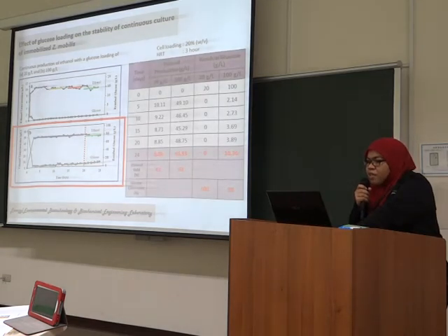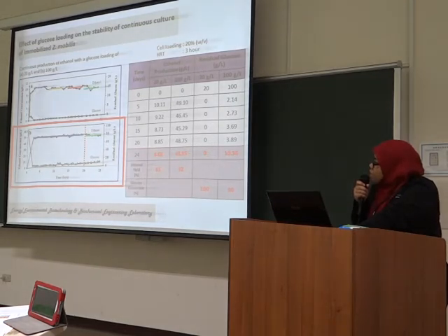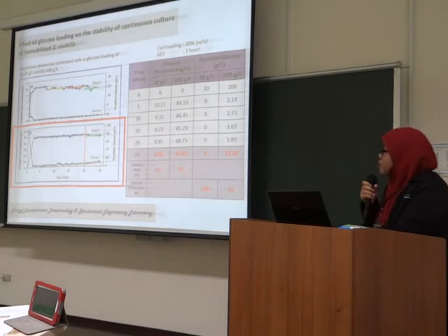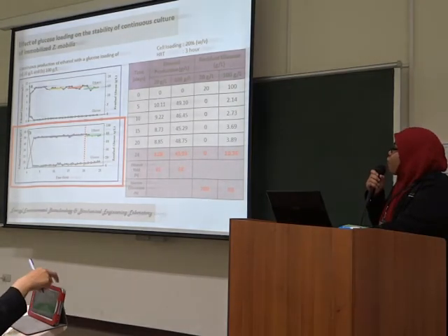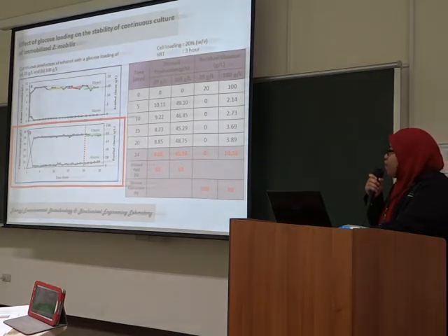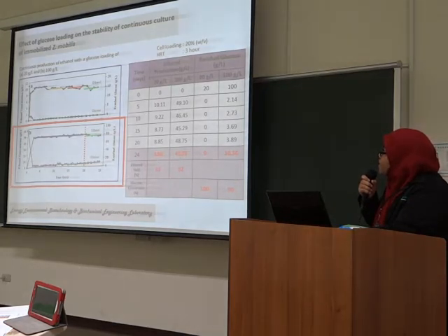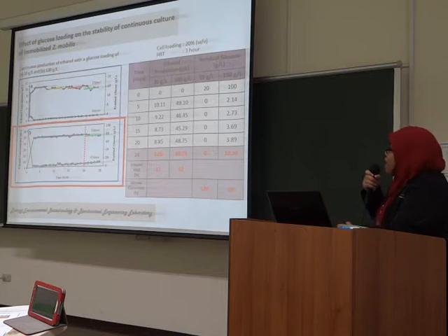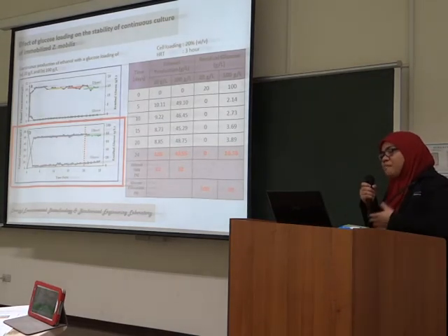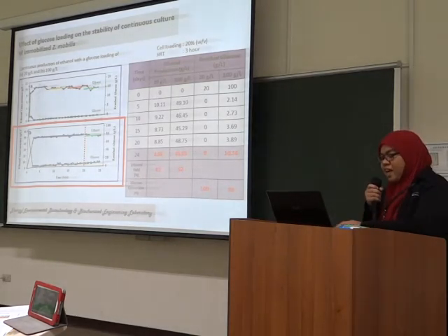You can see after 24 hours, the ethanol production for 20 gram per liter is only 8.09 gram per liter, with the ethanol yield just around 81% of theoretical yield. But for 100 gram per liter, we can get 92% of theoretical yield. For residual glucose, even for 20 gram per liter of initial glucose, we can get 100% glucose conversion, but it's not guaranteed this ethanol production will be the optimal condition, because I think for this case, the carbon source for cell growth might not be sufficient, so it could reduce the ethanol production in the future.